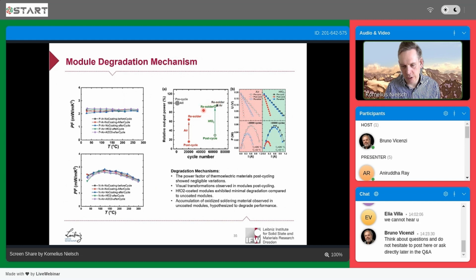So we can see that in principle, there's no degradation of the thermoelectric material if we pack it in hafnium oxide. There's some slight degradation if we pack it with aluminum oxide, but the weakest point in the whole device is up to now the soldering, but it's still already rather good for application. But I think we can go to more robust solders in the future to make the module more durable, for really long-term applications.